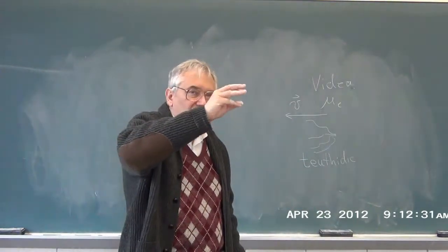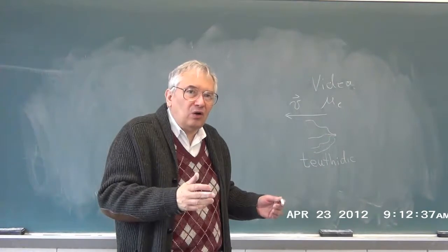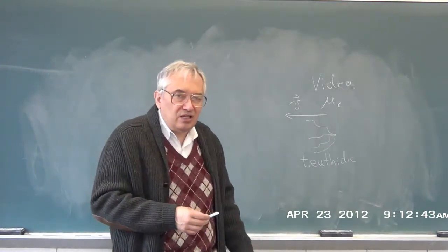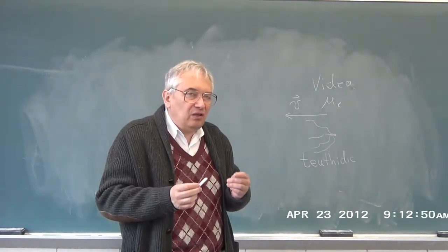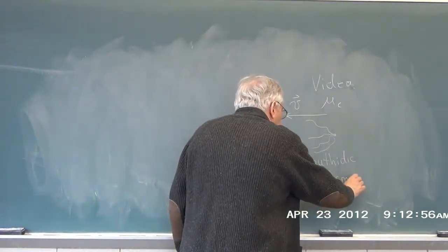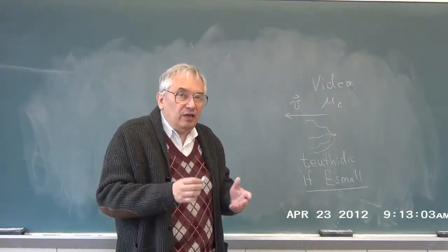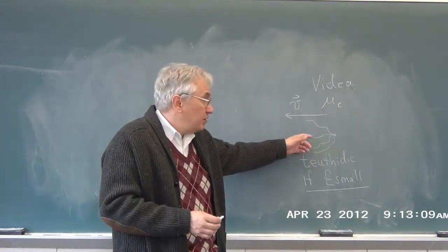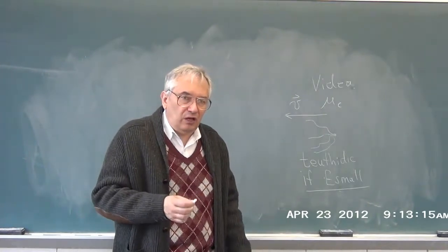The chain moves like this. We appear to be in the low field regime. That is, if you go to lower and lower electric fields, things move more and more slowly. The extension becomes less and less. But we seem to be in the low field regime. If we are in the low field regime, and that is a very big if, because there's plenty of room for going to very low fields, and gee, it does change. But if you are in the low field regime, then the fluctuation dissipation theorem and linear response theory says that this class of motion is how star polymers diffuse through polymer solutions.